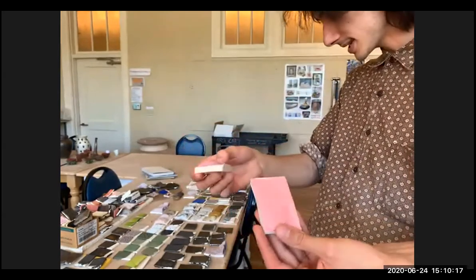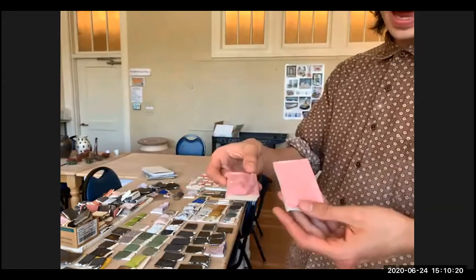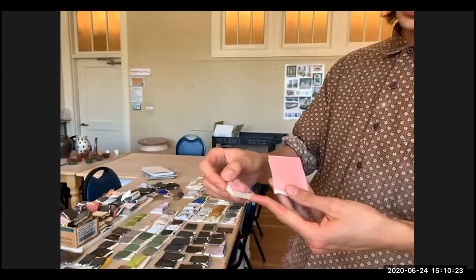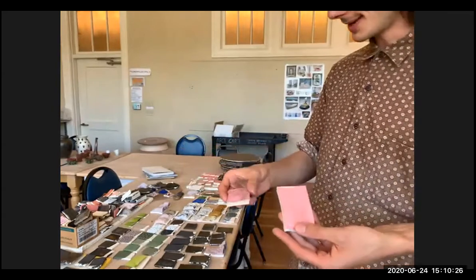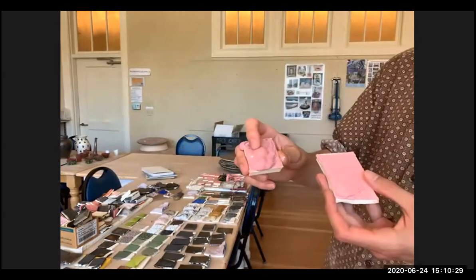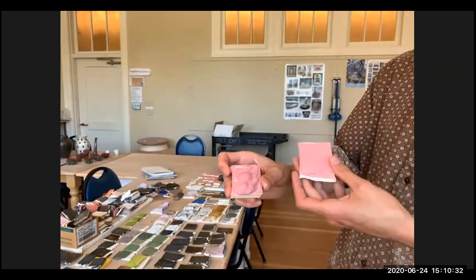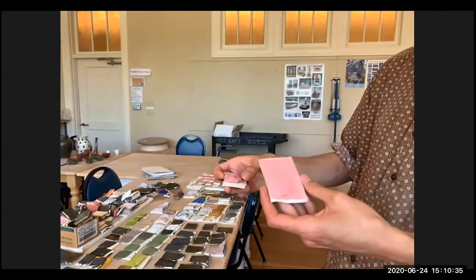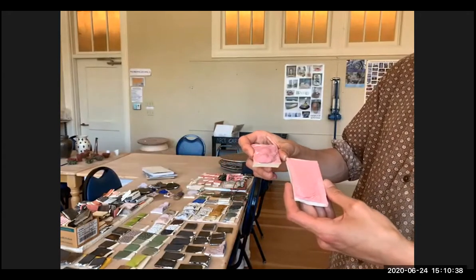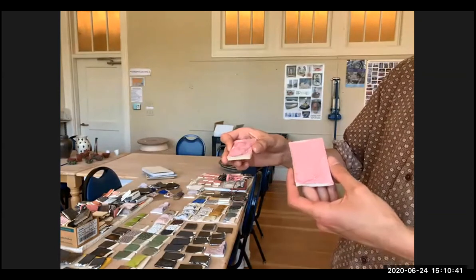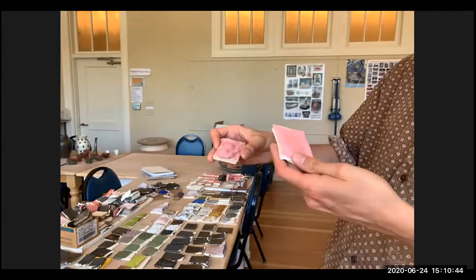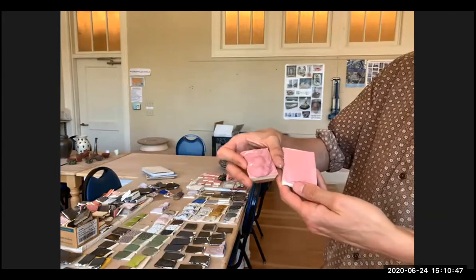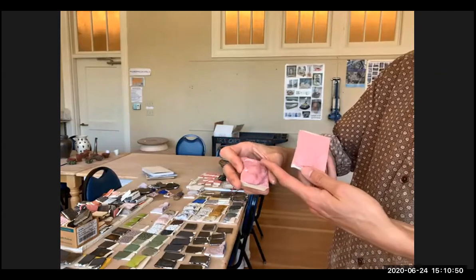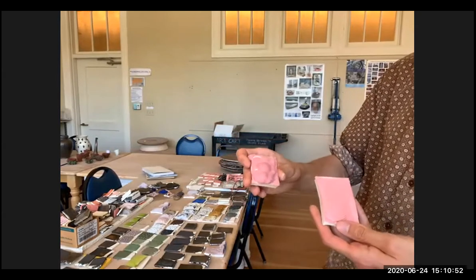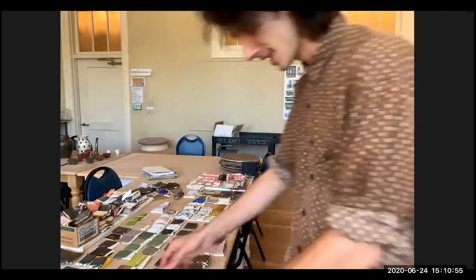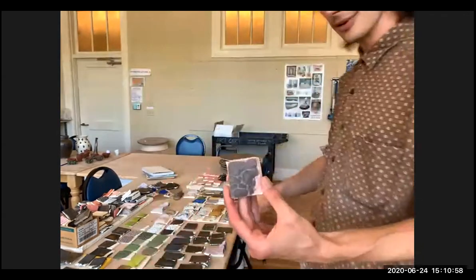These I've been investigating more or less serious matte glazes that use silicon carbide. I say serious mattes because the reason that these aren't bursting is because there's a layer of matte crystals on the surface. The reason matte glazes are matte is because they form silica and alumina crystals on the top that make a matted surface. And it's actually a stiff layer of glass during the firing. So that stiffness on the surface allows the carbon dioxide to be trapped and create those inflated forms.